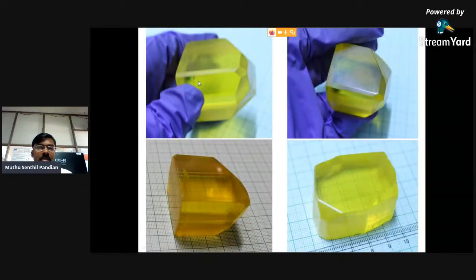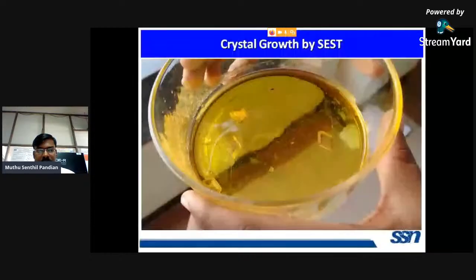And this is the 4-nitrophenol derivative single crystal. From these crystals, we have identified the type 1 and type 2 SHG elements, and we have planned to mount them at the bottom of the glass sample. We are yet to grow along the SHG element direction for these 4-nitrophenol derivative single crystals.